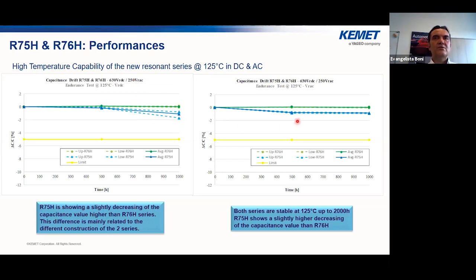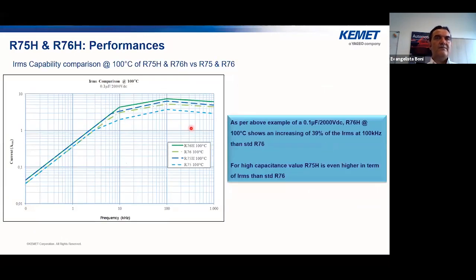Here it is also possible to see, in AC at 125 degrees, similar characteristics as observed in DC. Here it is possible to see another important characteristic. These high temperatures are not important only to work at higher temperature, but they can also work at the same temperature as the current series, but with higher ripple current and higher power density. And that's a great example.